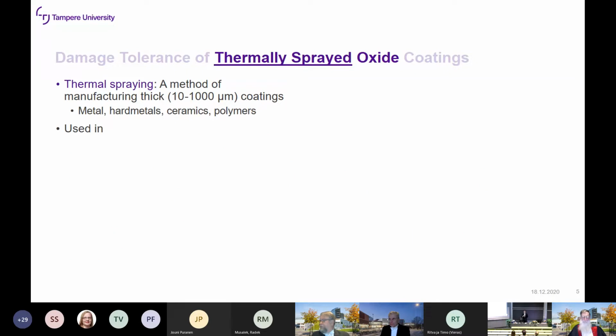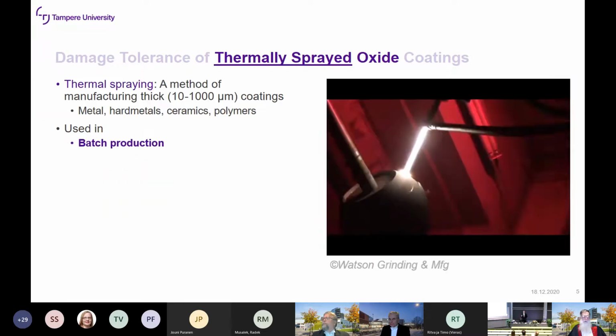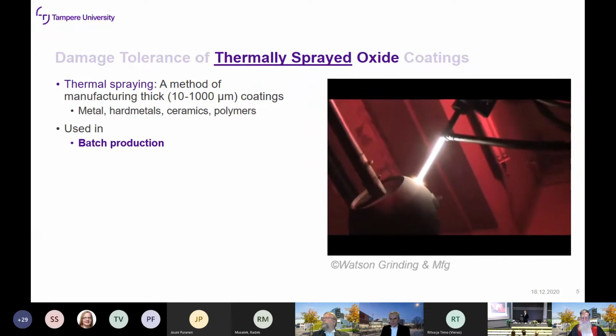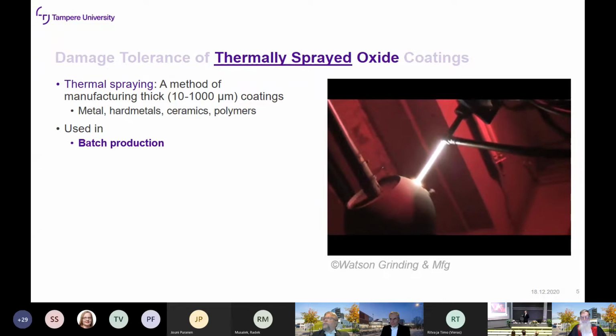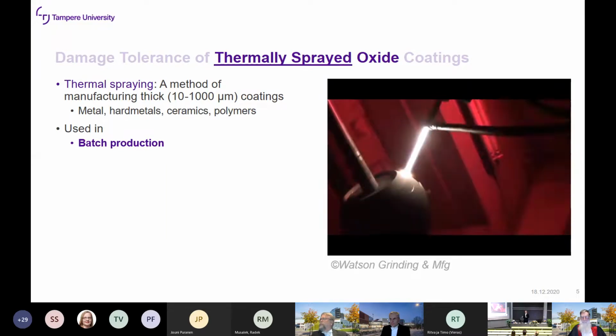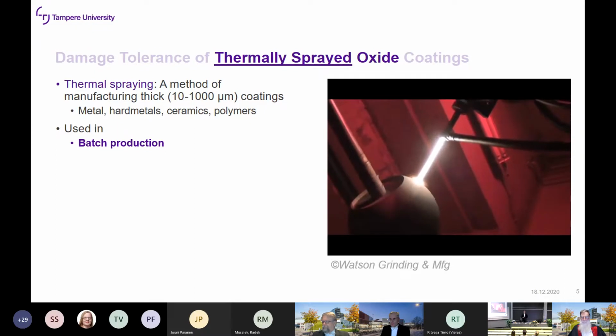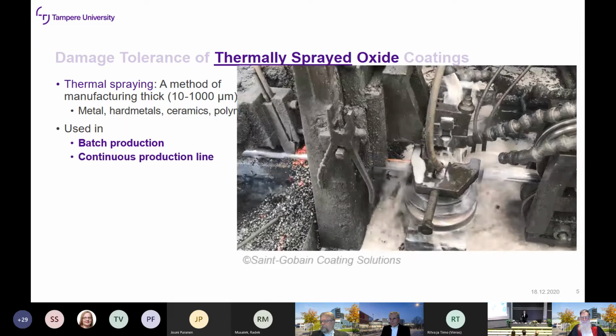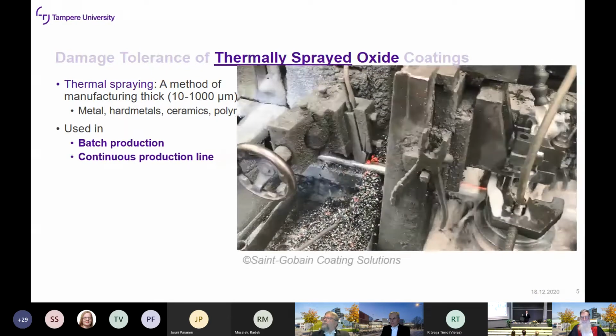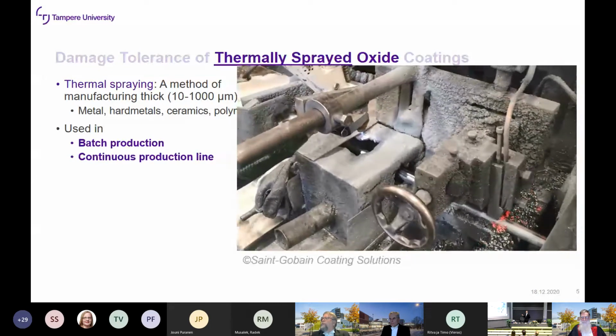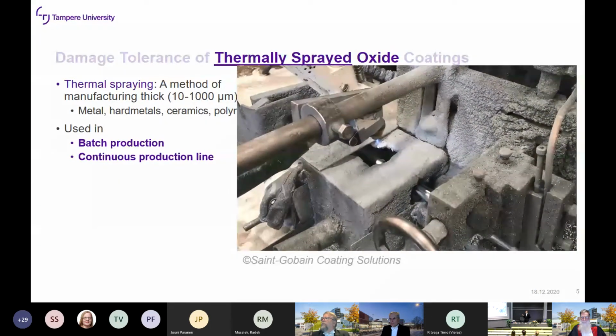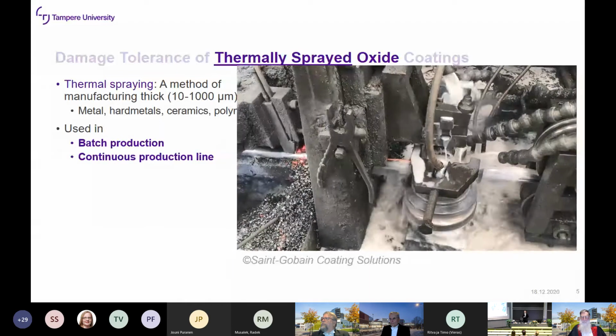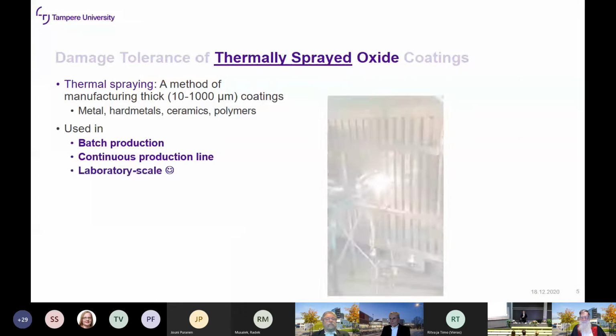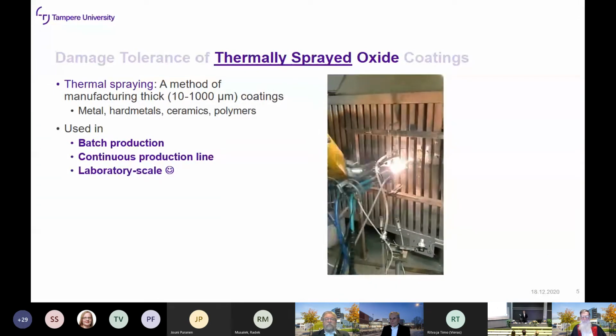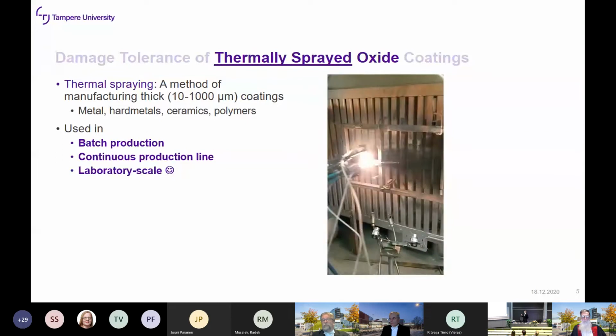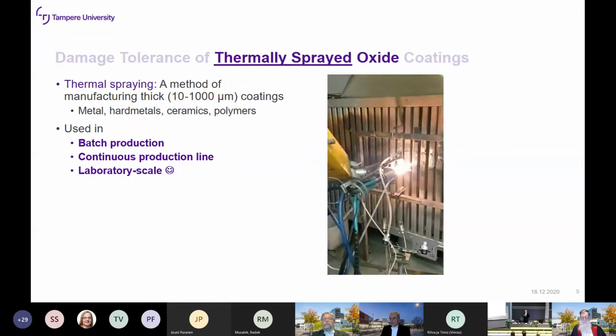These coatings are used, for example, in batch production, such as this ball valve for process industry that's being coated with a hard metal coating. We coat one ball and we stop the process, switch it up, and resume with the next one. It can also be used in continuous production lines, such as this coating of a stainless steel welded tube, where the weld area is void of corrosion protection, and we need to apply a new zinc layer on top of this to re-galvanize the galvanized metal. And it can be used in laboratory scale. Like in this case, there is a coating for my study being made. So even really small pieces downstairs here at the university.